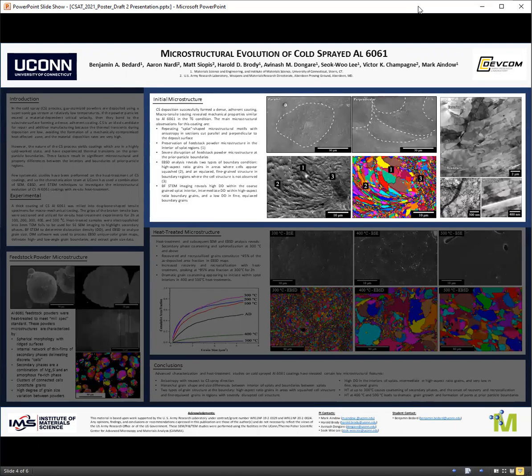After cold spray deposition, these powders have formed a fully dense coating with properties similar to aluminum 6061 in the T6 condition. However, the microstructure of this material appears very different from conventional T6. The thin film distribution of the secondary phases has been preserved within the interiors of the prior particle regions. Severe plastic deformation can be seen on the prior particle boundaries.